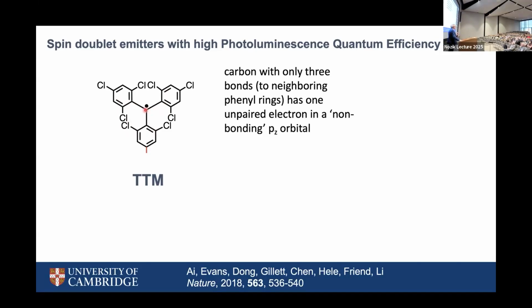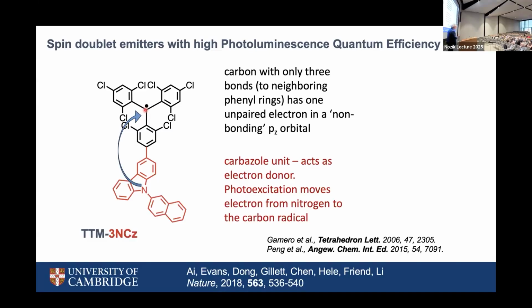There is quite a literature on these, and until recently, these were rather dull, literally not very bright. But in various ways, it's proved possible to make them very bright. There's important work that came originally from a group at Barcelona, where if you do some more chemistry, here's a molecule where we've got a carbazole linked on to the TTM. The optical transition that makes it bright is one that moves an electron from the lone pair on the nitrogen to pair up with the electron on this radical carbon. And that's an allowed transition. And it absorbs moderately well. It emits very, very efficiently.